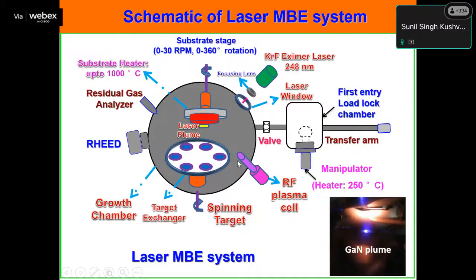The main chamber is always, 24 by 7, under ultra high vacuum, 10 to the power minus 10 millibar. In the load lock, we can even heat the substrate up to 100 to 200 degrees Celsius. This chamber also has a roughing and turbomolecular pump, so it will reach at least the minus 5 to minus 6 range. After that, we can open the gate valve and transfer the sample from here to the main chamber.